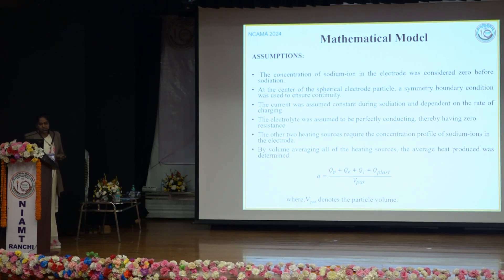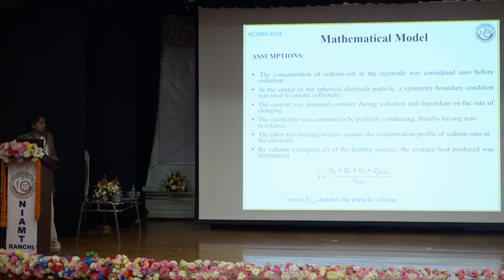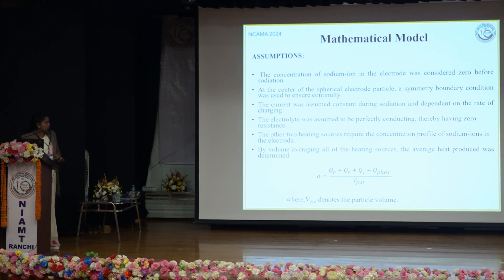The following assumptions were made while applying these models: the concentration of sodium ions was considered zero before sodiation; at the center of the spherical electrode particle, a symmetry boundary condition was used to ensure continuity; current was assumed constant during sodiation and dependent on the rate of charging; the electrolyte was assumed to be perfectly conducting with zero resistance. All types of heat — polarization heat, entropy heat, joule heat, and plastic deformation heat — were averaged with respect to particle volume.